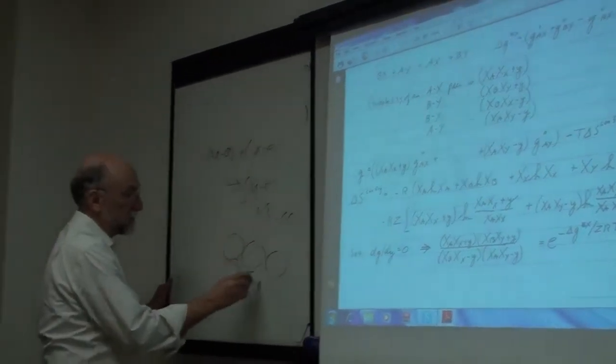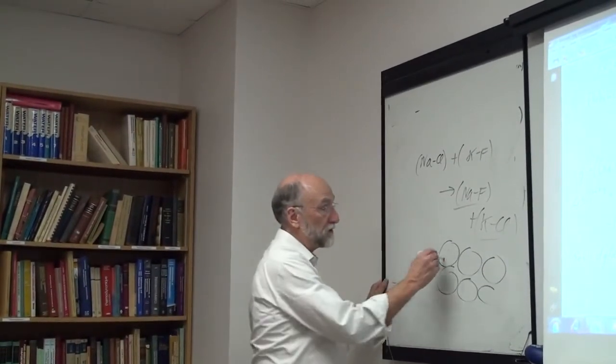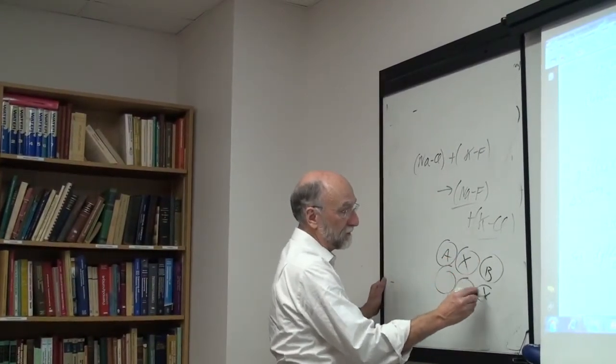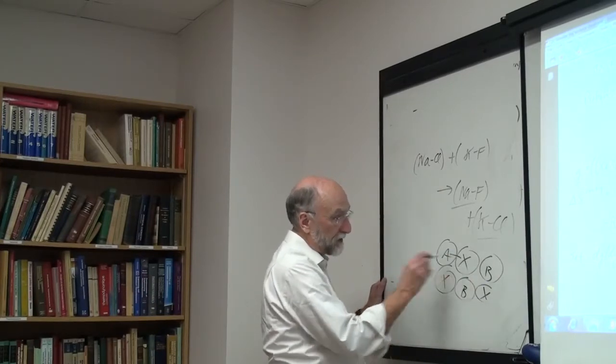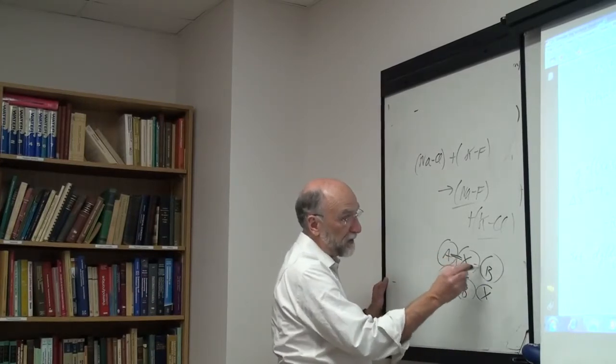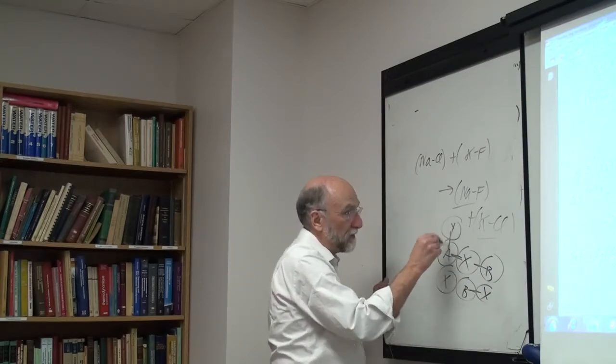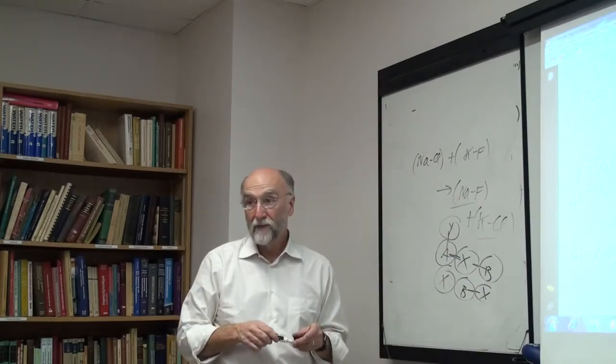This is like the quasi-chemical model. In the quasi-chemical model, on the single sublattice, we mix the AB, AA, and BB pairs over pair sites. Now we're doing the same thing. We're mixing the AX pairs, the BX pairs, the BY pairs, the AY pairs over pair sites.